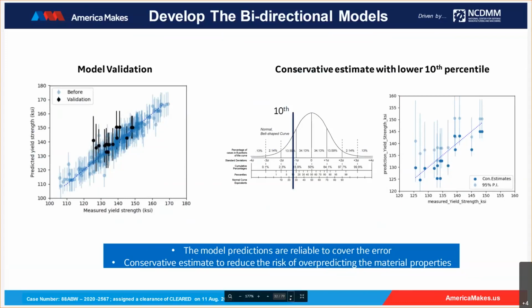So to handle the prediction uncertainty, we would like our predictions to be conservative rather than optimistic, to stay safe for additive design and aerospace design cases. For this, we introduced the concept of conservative estimate, which is based on the lower 10th percentile of the BHM prediction. The BHM prediction assumes a Gaussian distribution for all the cases. For the Gaussian distribution, we calibrated the mean value based on standard deviation to locate the lower 10th percentile. The lower 10th percentile is used as the conservative prediction.